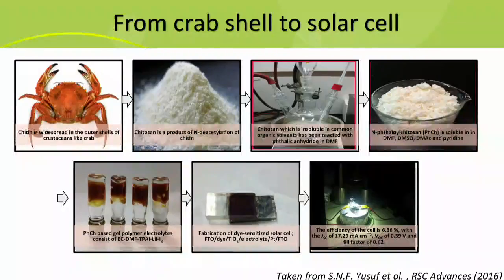So of course, in this process, we have to look into many parameters. One of the parameters for this paper actually is we use a mixed salt, and we realized that its efficiency is much better than the single salt. The mixed salt actually gives an efficiency of 6.36 as compared to the single salt of 5. So that's an increment. So we have to keep on working until we get better, hopefully we get 10. Yeah?